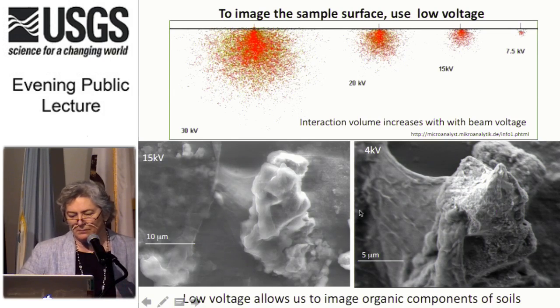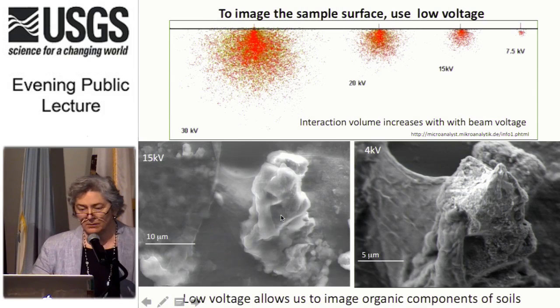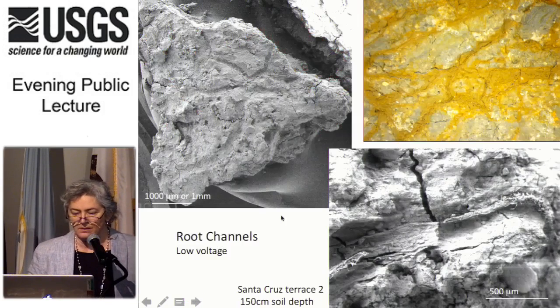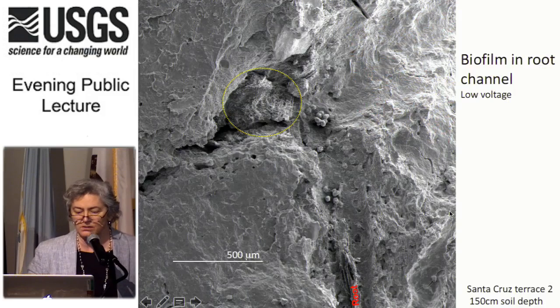But the other thing is, by going back and forth, you can see that this looks like one solid piece of a mineral, but it's actually made of different grains. So using these different techniques can tell us different things. So we're going to look at, now this is the deep where the root channels used to go, and you see this discoloration. That's probably things that have been exuded into this clay matrix from the passage of these roots. And here it is in a bigger chunk under the SEM. And then here's the small root. There's actually some root material left in here, and you can see root hairs. And we're going to look in closer onto these root systems.